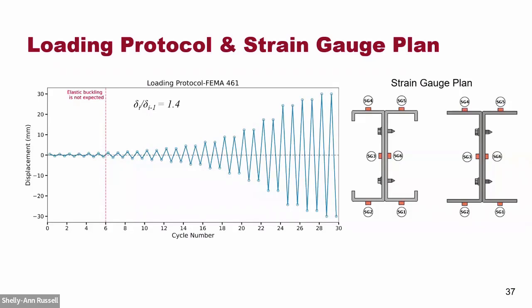We have used the FEMA 461 loading protocol. So it's a continuously increasing protocol. Each step has 2 cycles with the same amplitude. The ratio with this amplitude is 1.4. And we have the strain gauge plan to install for each section at the flanges and also at the webs to see whether these sections work together or not.